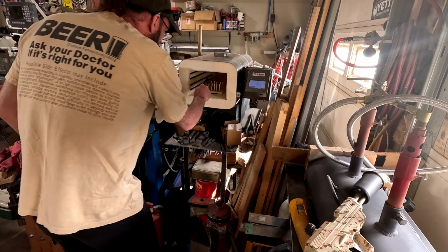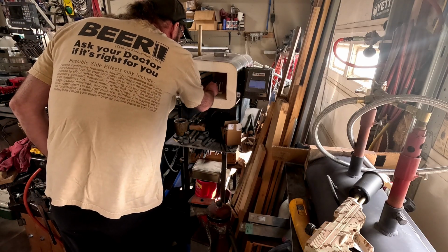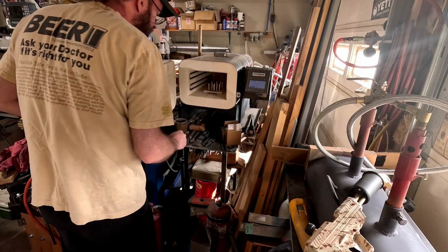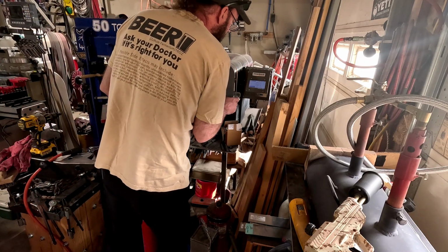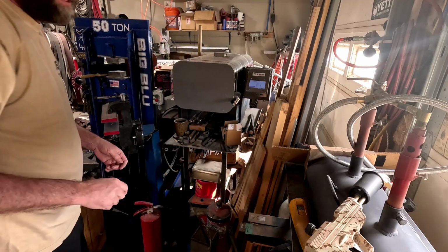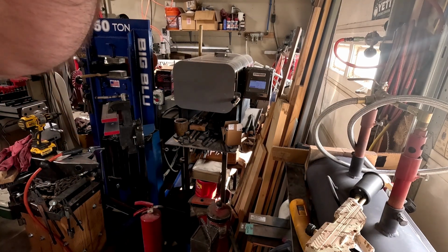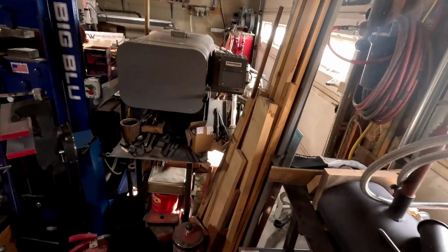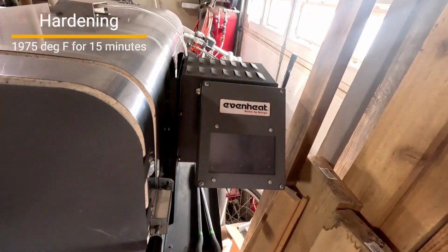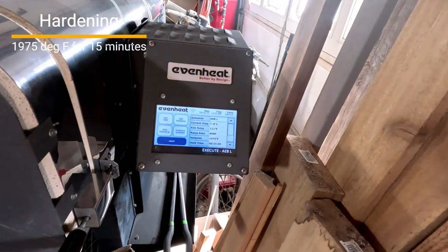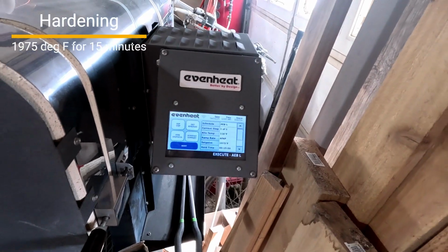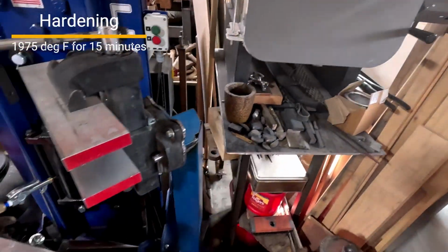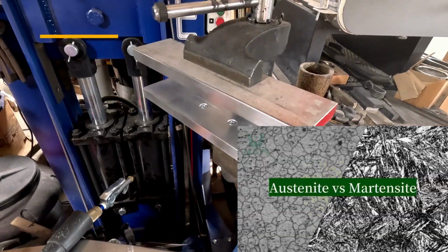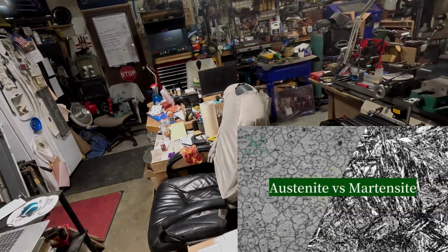After enclosing the blade in a stainless steel foil packet, we are ready to harden the steel. The first step is to heat it up to 1975 degrees and cool it down very quickly. We will be using 2 aluminum plates connected to a vise to clamp the blade tight and let conduction draw the heat out of the steel. This process converts the austenite into martensite, which is very hard but makes the steel brittle.